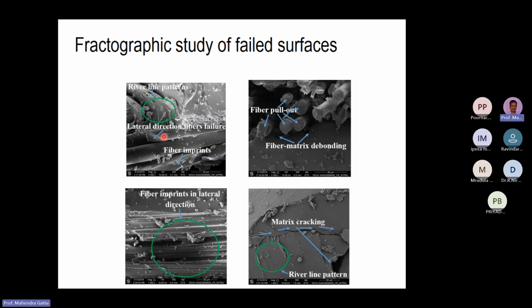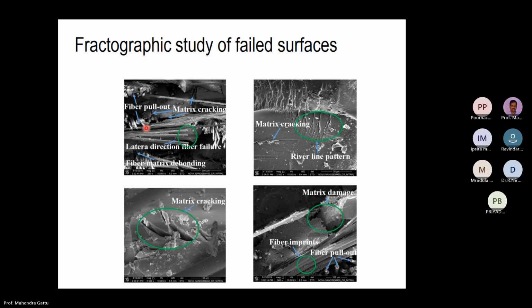And at higher loading rates, we are finding matrix fiber debonding, and there is a lot of breaking in the lateral direction. So if the load is applied in this direction, in the perpendicular direction also the fibers were breaking. So similar thing at 500 we also found there is a lot of matrix microcracking, means at very high loading rate. So this is what we reported to the journal, and the editors and reviewers accepted it. So we had our first paper together.